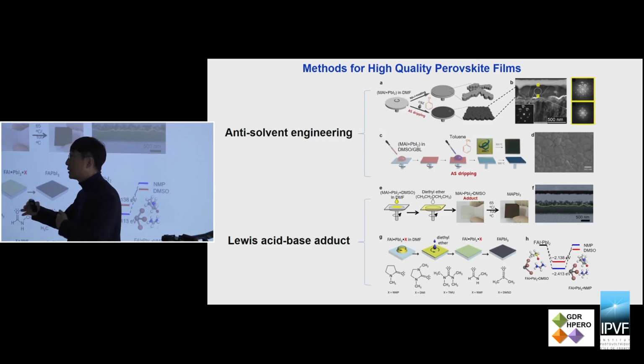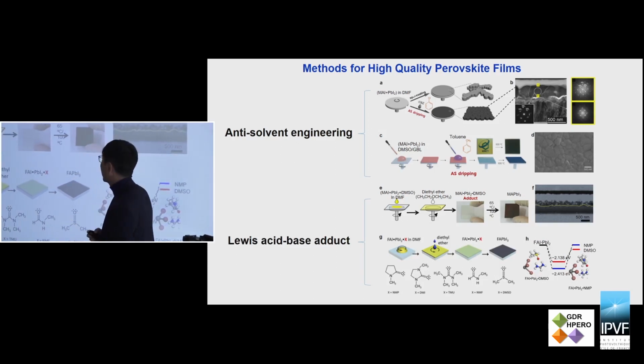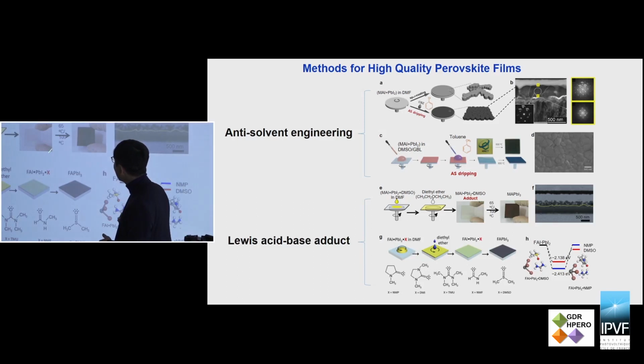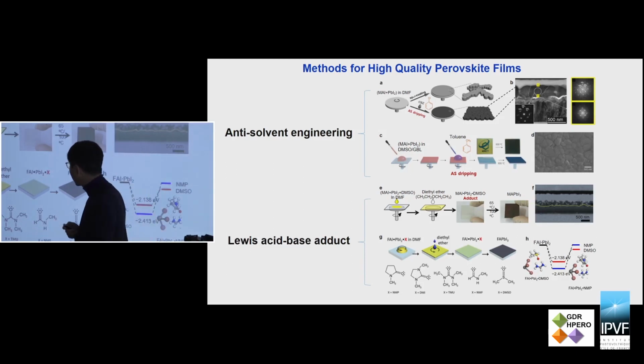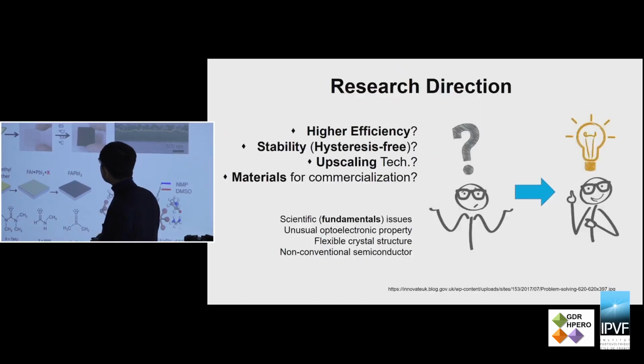Otherwise, because the process to make the perovskite film is very fast, you cannot control the perovskite film. So we need an intermediate phase anyway. If you undergo the intermediate phase, then you can make high quality perovskite films. For the Lewis base candidate, you can use any kind of these polar aprotic Lewis base materials.